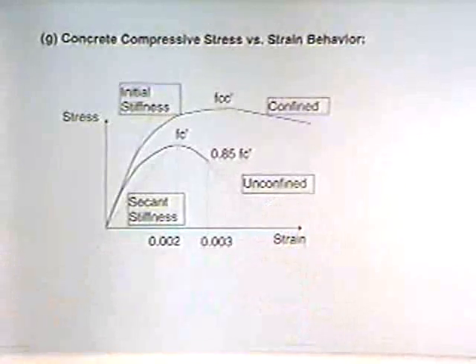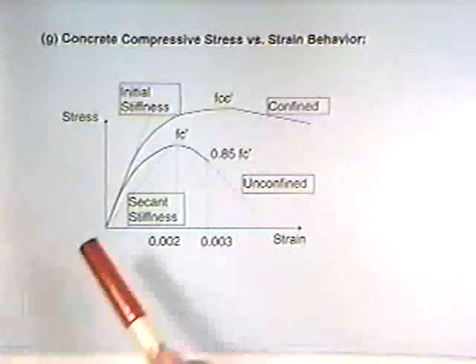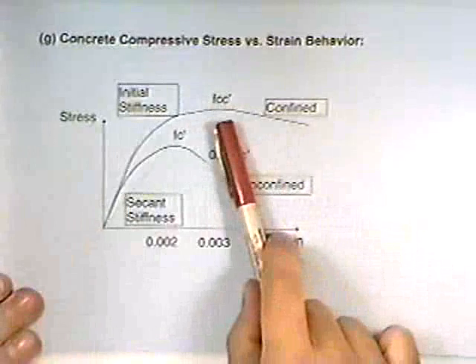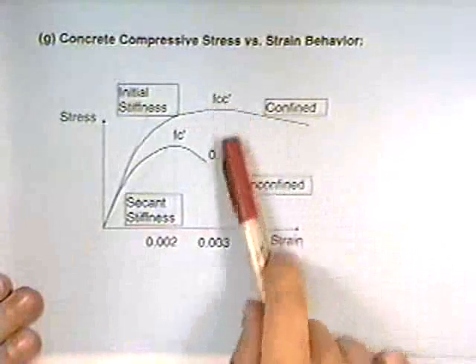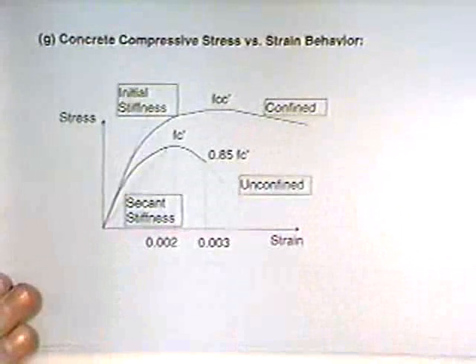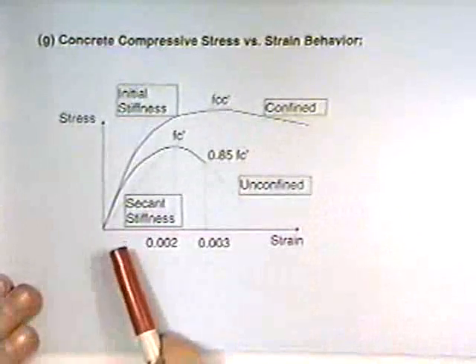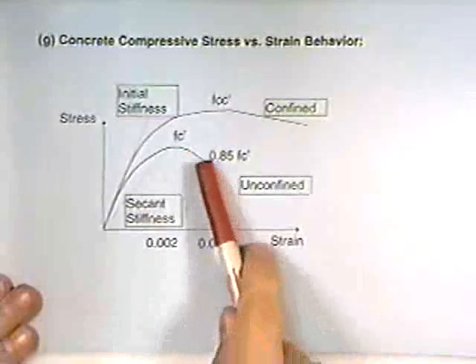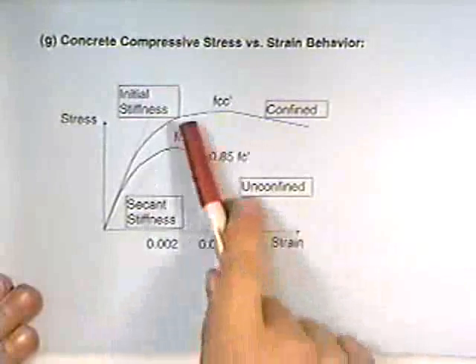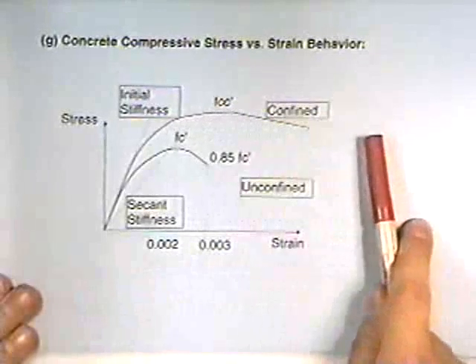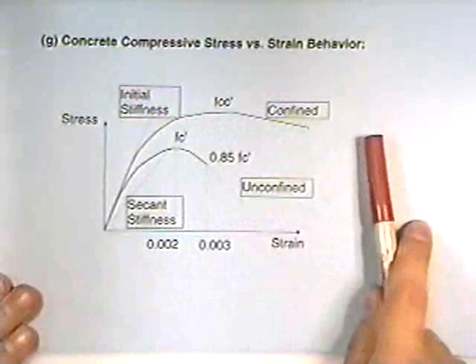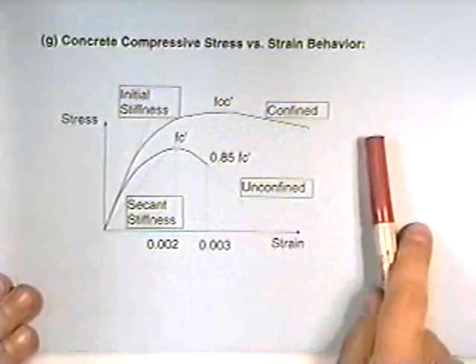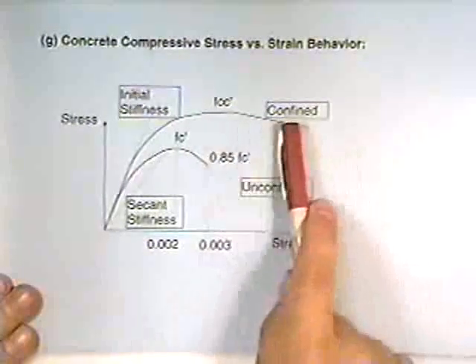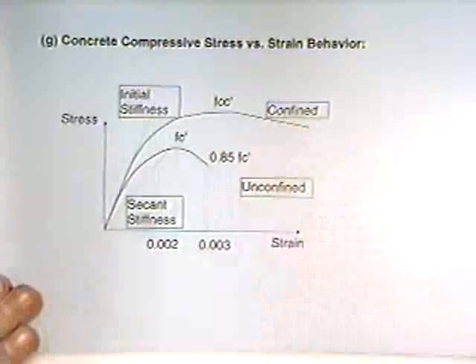Now, just think about if you take this cylinder and you try and confine it laterally. What's going to happen is that the cement mix that you get can have a lot more strength. That's a value that's referred to as f'cc, and that increase in strength can go up from 20% to maybe as much as 50 to 75%. The other big thing to note is that when it's unconfined, this point drastically fails very fast. It's very brittle. If you confine it, this level of strain can go out to a very large range, which means it's more ductile. And for earthquake zones and when you're dealing with blast loads and things like that, you would always want your sections confined just based on this property alone. It's increased ductility. I'm not going to talk much about that.